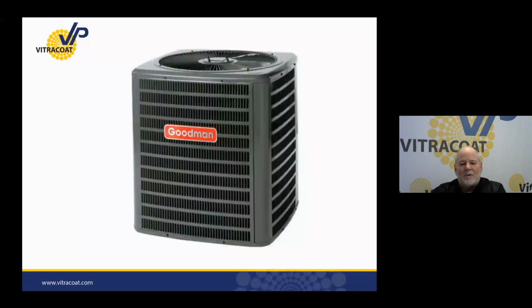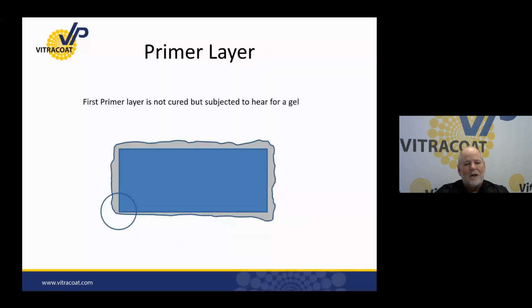Because if you're not aware of what environment your part is going to be exposed to, layers can be a very, very good option for you. And you can do a polyester top coat, a super durable top coat. You can use a zinc primer. You can use an epoxy primer. You can use a polyester primer. It just gives you the ability to take that particular part that has these sharp edges, put one layer of primer on first. I prefer to gel the primer layer and not totally cure it. And down at the bottom where I've got very limited film build on that edge, then I come back with my top coat and I've just got two barriers of protection that are mono-baked together to give me that.